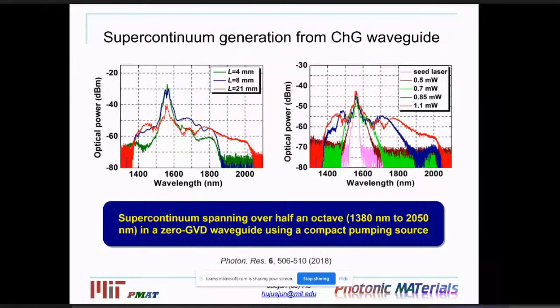And what we're seeing here is that as you increase the pump power, you can of course extend the spectral coverage of the supercontinuum. And ultimately, the spectral coverage is limited by the power output from our compact pumping source. So this is one of the trade-offs here. If you want larger wavelength coverage, you have to go with a desktop femtosecond laser that offers much more power. But again, that defeats the purpose of on-chip integration.